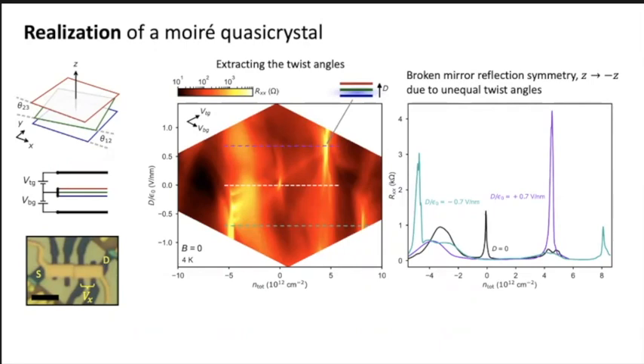You know, we've been hearing a lot of fillings 1, 2, 3, 4 over the past few days. Okay. So the band insulator, the nu equals four state here. This should be an insulator, except that of course you have the charge neutrality point from the top layer still conducting. So it's not a full insulator, but it's still a highly resistive state, which corresponds to the band insulator for these bottom two layers. Okay. And that's how we know that we have a certain angle, 1.4 degrees, okay? Because this density corresponds to 1.4 degrees for a filling of the bottom two layers.